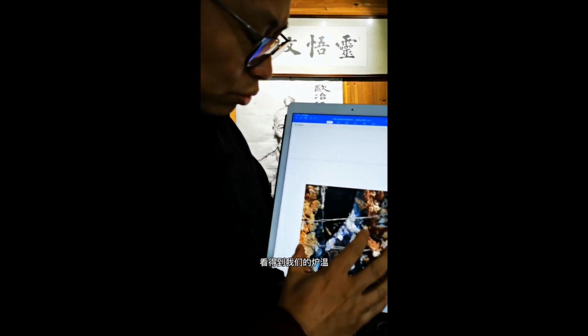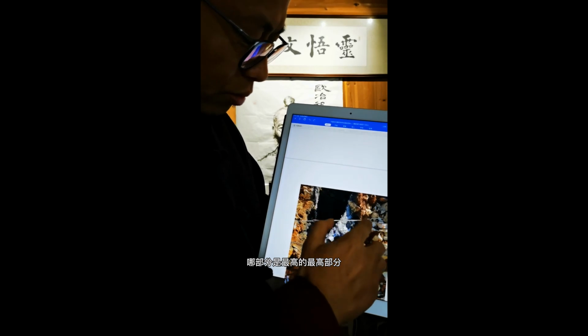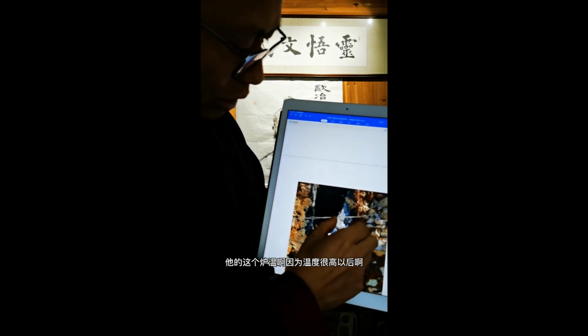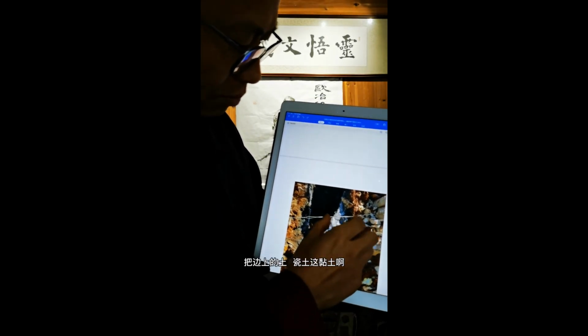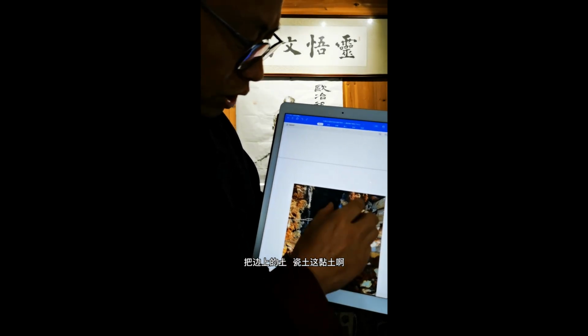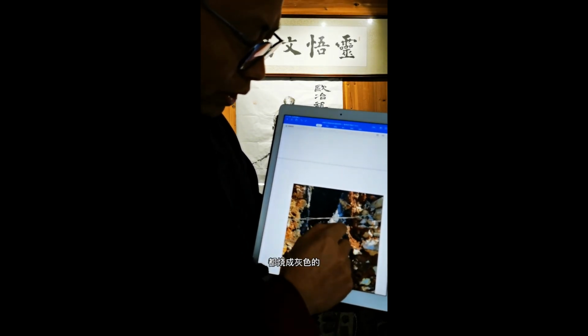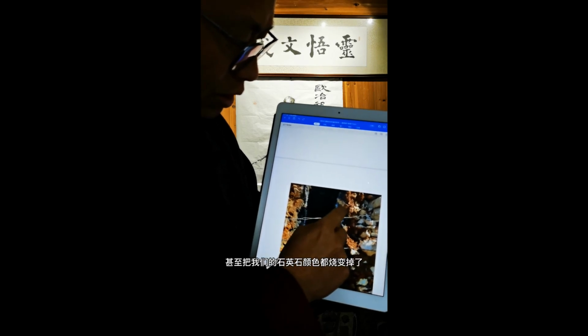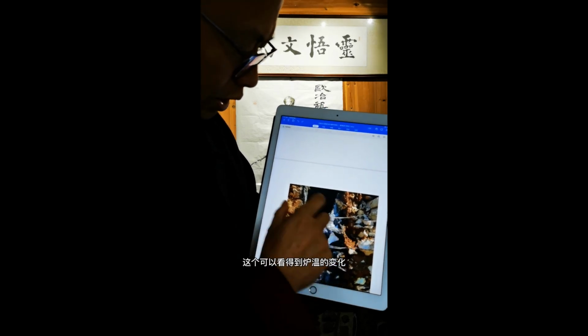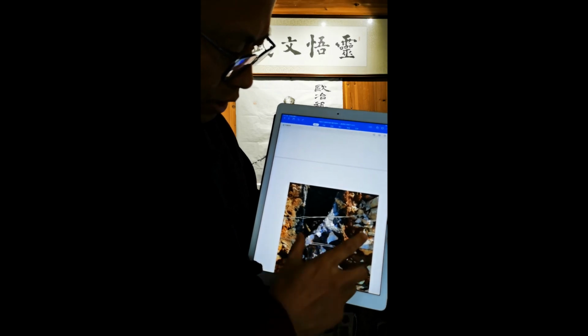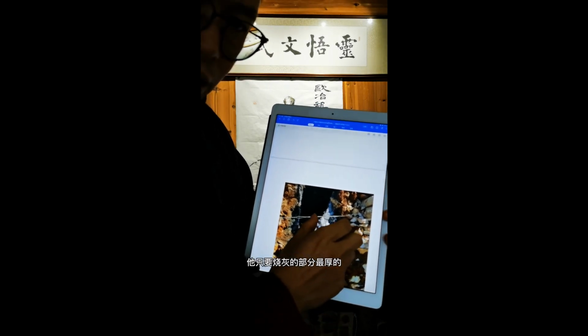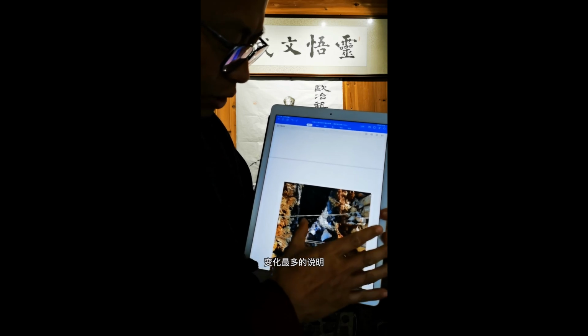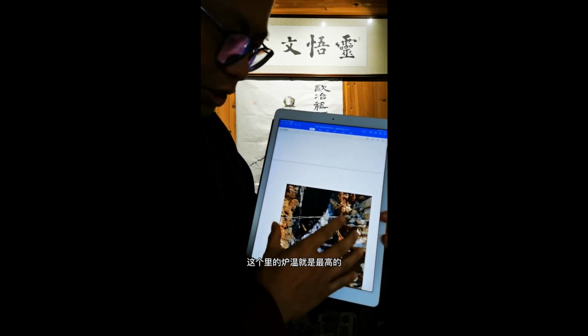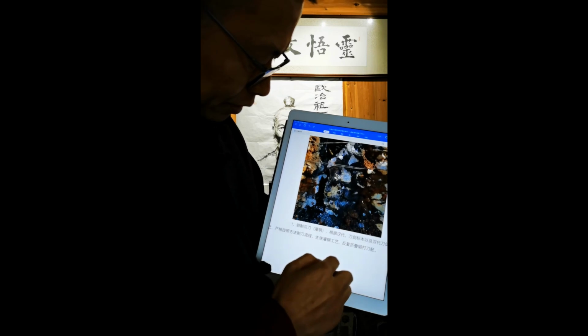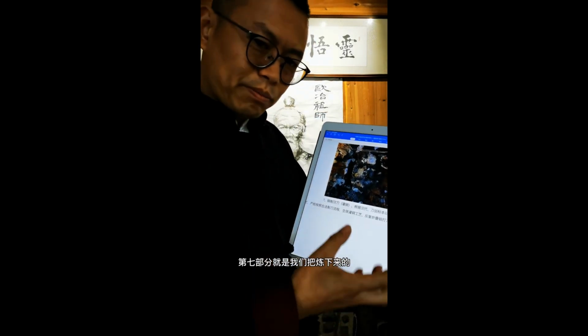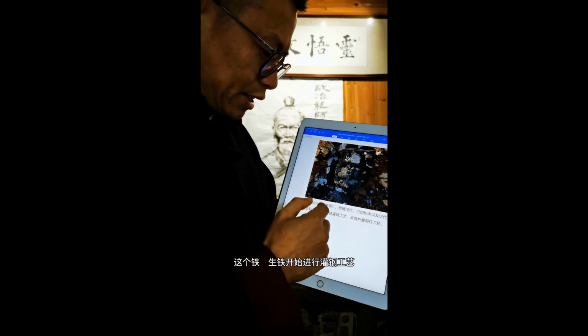And after dissection, we found at which point the temperature was the highest. Because of the extreme high temperature, the clay was burned gray in color, and the quartzite also changed its color because of the high temperature. If the gray area is very thick, this means the temperature used to be very high in the furnace.